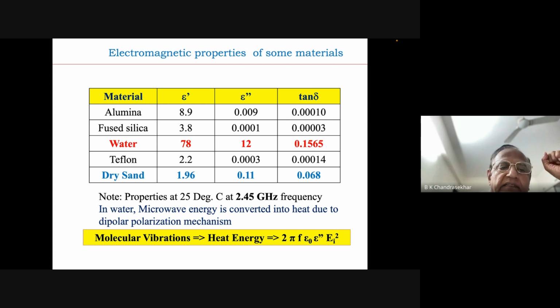Now, if you look at Teflon, which is a plastic material, the epsilon double prime is very, very low. It hardly interacts with the microwave. Therefore, you can very safely use Teflon material in a microwave oven because it will not absorb any heat. Nothing will happen to the Teflon.